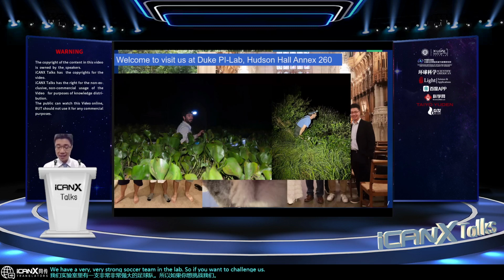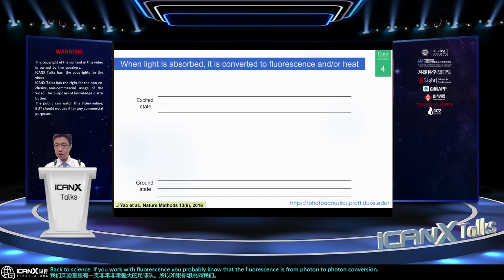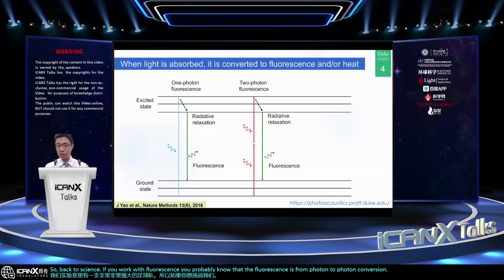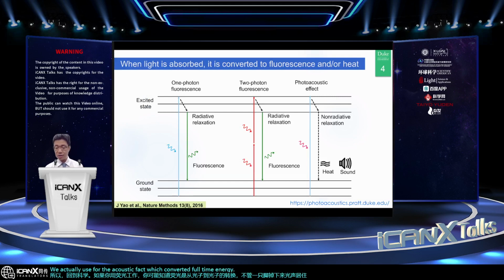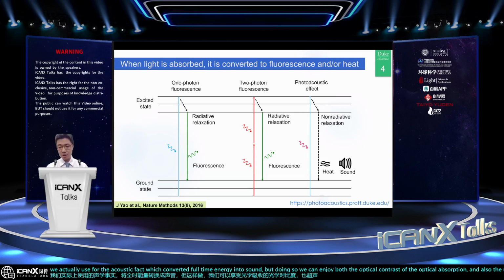Back to science. If you work with fluorescence, you probably know that fluorescence is from photon to photon conversion, no matter one-photon or two-photon fluorescence. For photoacoustic imaging, we actually use the photoacoustic effect, which converts the photon energy into sound. By doing so, we can enjoy both the optical contrast of the optical absorption and also the ultrasound resolution and penetration depth, which is not available by other optical imaging modalities.